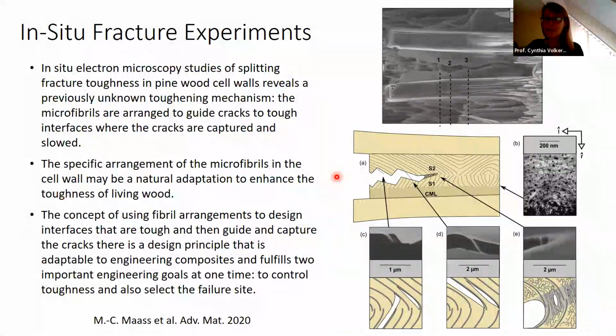And we wanted to understand this fracture along the grain, which is otherwise difficult to study because it's unstable. In our case, because of our method, we could in fact watch this propagation along the grain in the wood. Now, wood is very susceptible to electron beam damage. The image you see here is from an SEM instead of a TEM, and that's where this study was performed. The TEM was too destructive. We had to work in the SEM. I won't go into the details, but we were able to watch these cracks propagate, and you see a sketch of what we observed here.